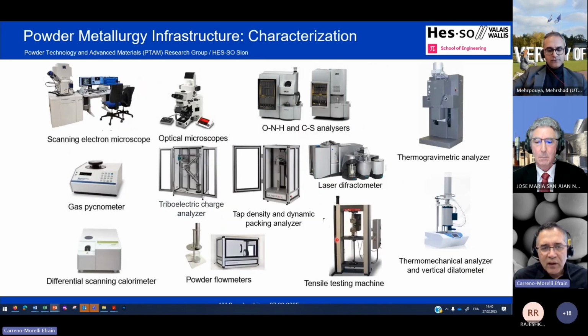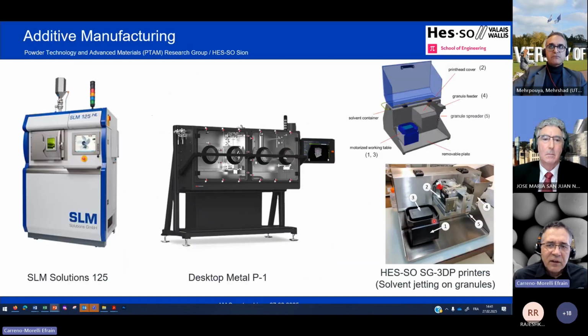We have state-of-the-art equipment to characterize powders and materials. Of course, microscopy, impurity analyzers, and all the necessary equipment to characterize powder particle size distribution and powder flow properties, especially useful for additive manufacturing techniques. We have dilatometers, calorimeters, all that. And in additive manufacturing, since 2017, we have the selective laser melting or laser powder bed fusion possibility. We have a Desktop Metal binder jetting 3D printer, which is a production machine with 1 liter of possible volume for build jobs. And we have our own technique.